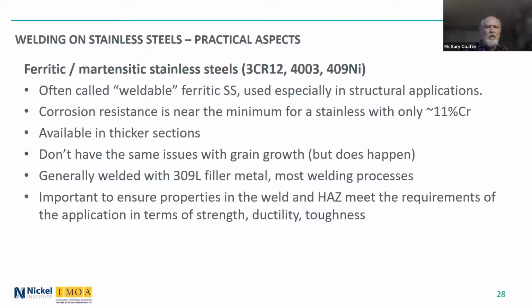They are available in thicker sections. I've seen them up to 25 millimeter, perhaps thicker is available. They don't have the same issues with grain growth, of fast grain growth in welding, although it does happen. They do grow in grain size in the heat affected zone. Generally, it isn't the same issues as with the purely ferritic. Generally, they're welded with 309 filler metal. Most welding processes are suitable there for them.